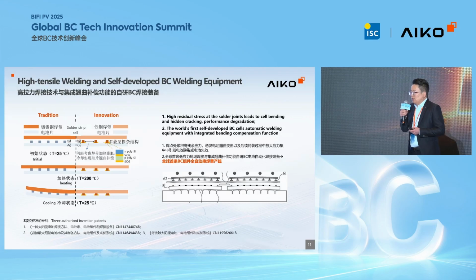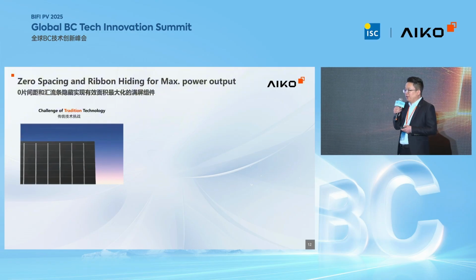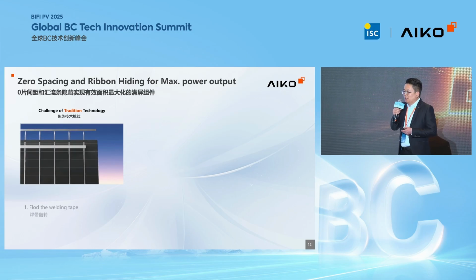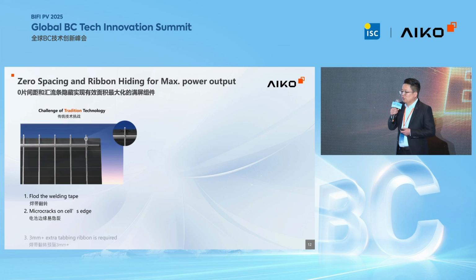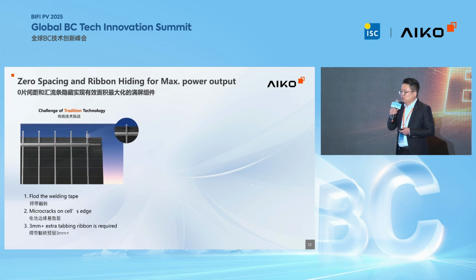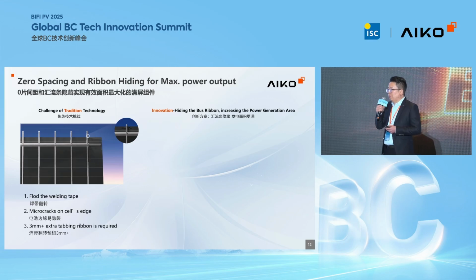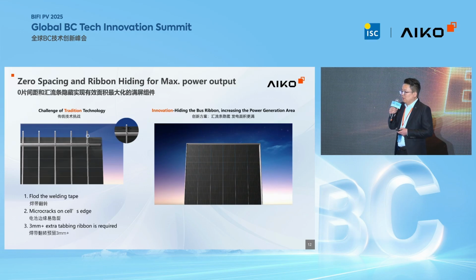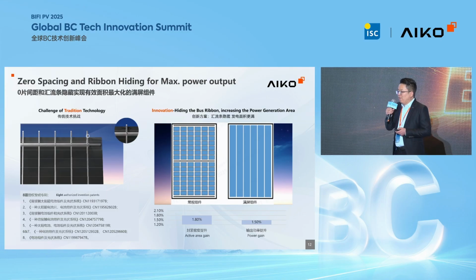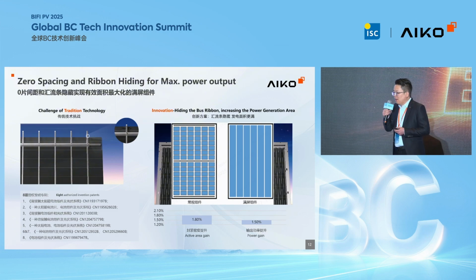In this equipment, the welding platform is slightly curved, and the strip is also in a hollow design to release the stress during the welding process. Another pioneering innovation from AIKO is the full-screen module. The traditional technology of folding the welding tab will lead to micro cracks on the cell edge. And another 3 millimeter extra tabbing ribbon space is required. So we hide the ribbon at the rear side. By this design, we can obtain a 1.8% gain of the active area and a 1.5% gain of the power.